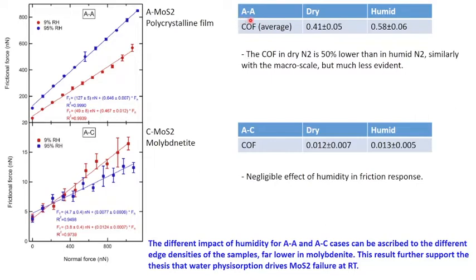So in the case of amorphous coupling, the coefficient of friction in dry condition is 0.41 and in humid condition is 0.58. This more or less is similar to the trend that we found at the macro scale, but is very different in terms of absolute value. And in particular, the difference from dry to humid condition is very different. But this is probably related to the fact that from the macroscale to the nanoscale, there are many differences which are related to the materials, to the different load that we are applying, to the different area of contact and others. So these are probably the reasons for the different behavior at the nano and at the macro scale.